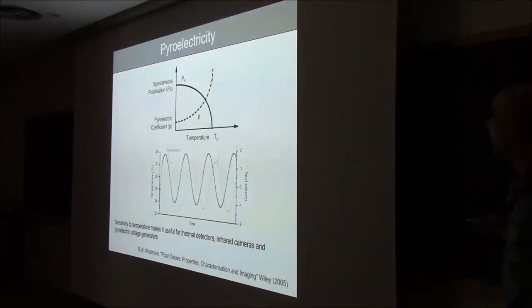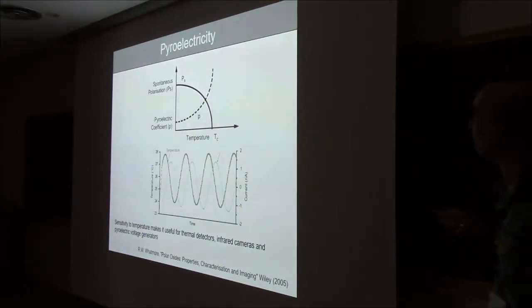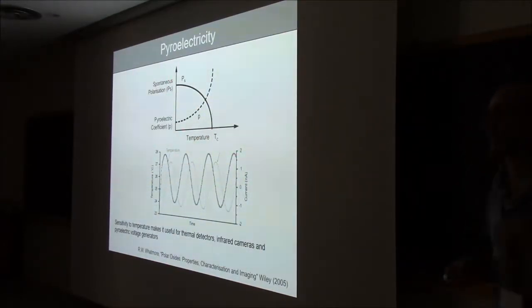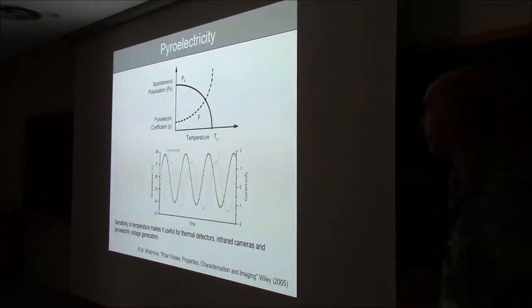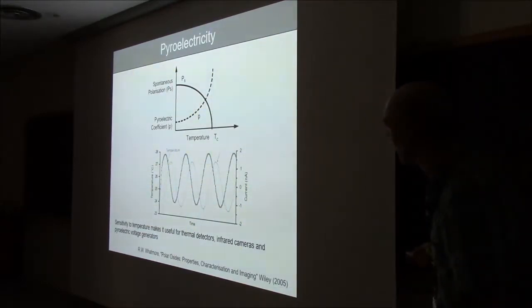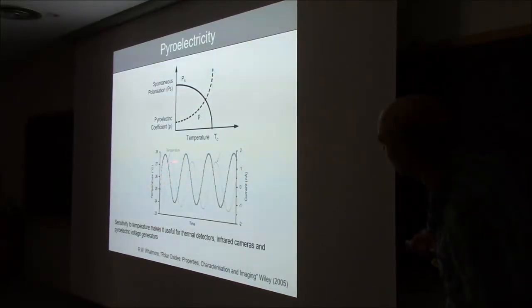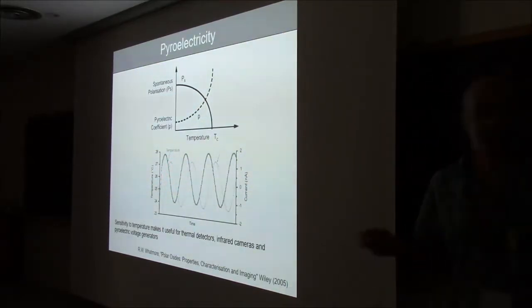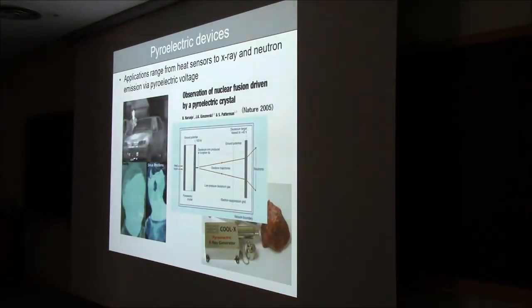Pyroelectricity. So, polarization depends on temperature. At high temperature, remember, your perovskite was not polar, at low temperature it is. In between, the polarization changes. So if you change the temperature, you change the polarization, and that gives you a current that you can measure, pyroelectric current. This is a typical pyroelectric measurement where you fluctuate the temperature and you see the current fluctuating. Where the change in temperature is maximum, the current is maximum. And these you can use for making temperature sensors.